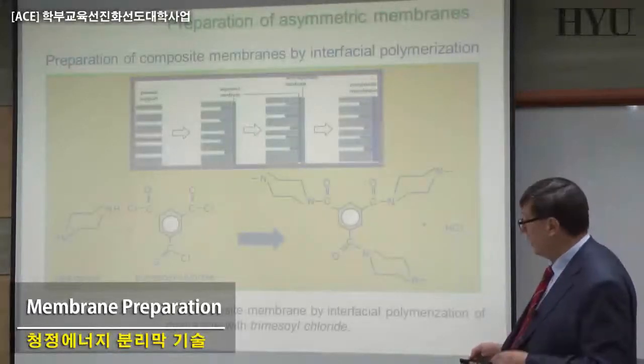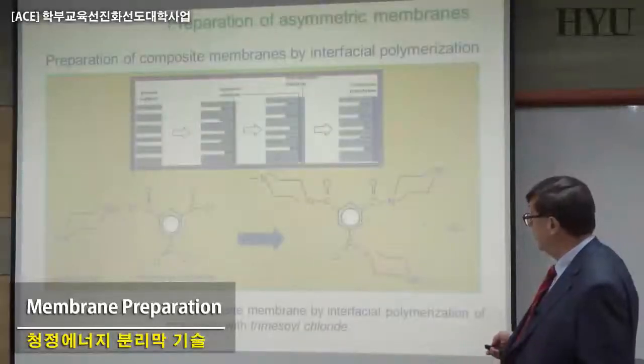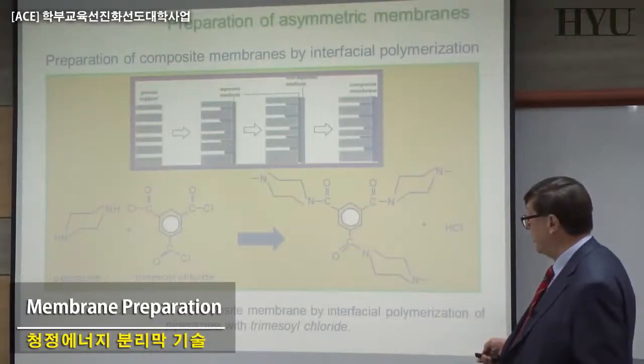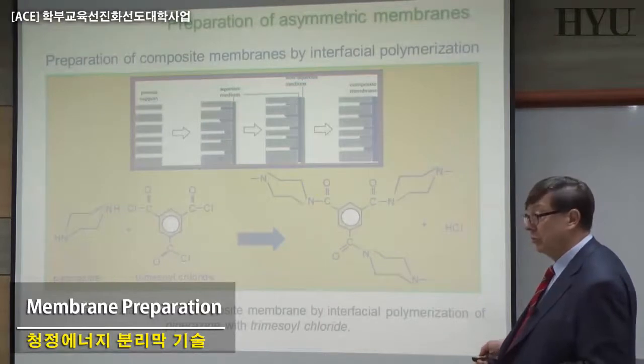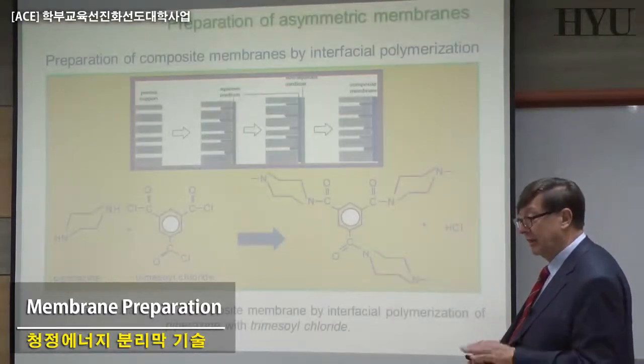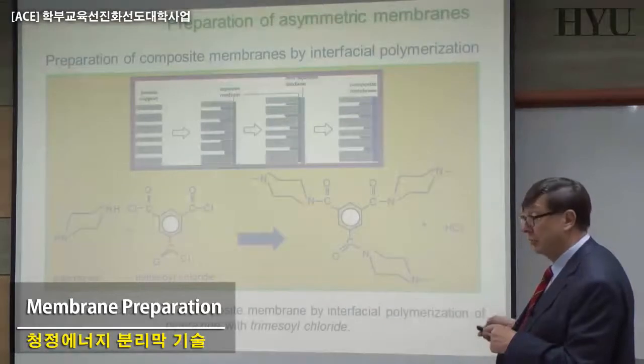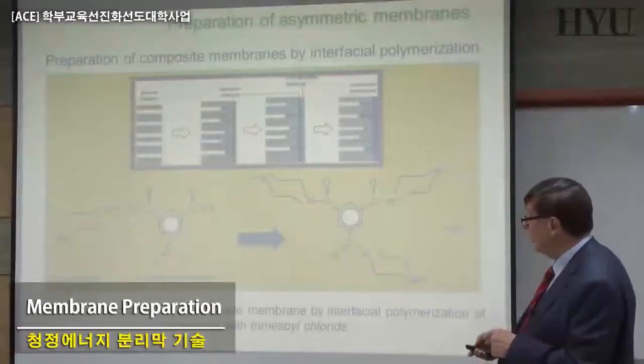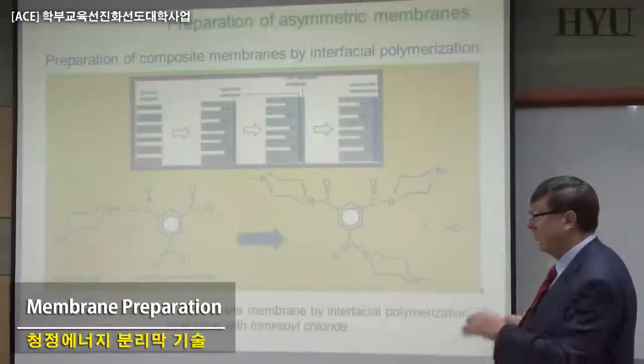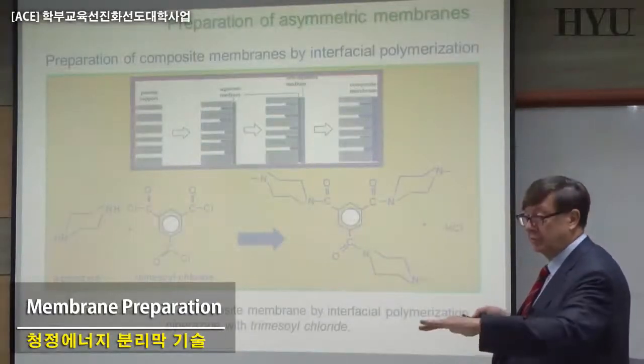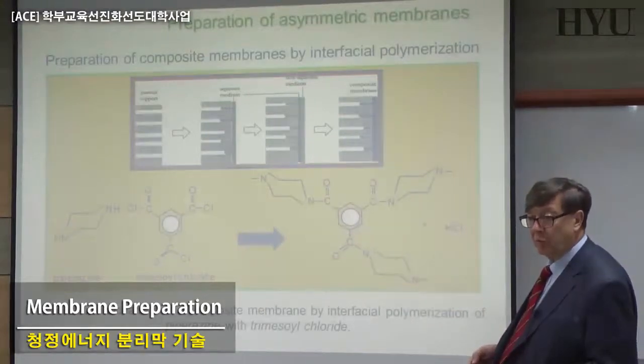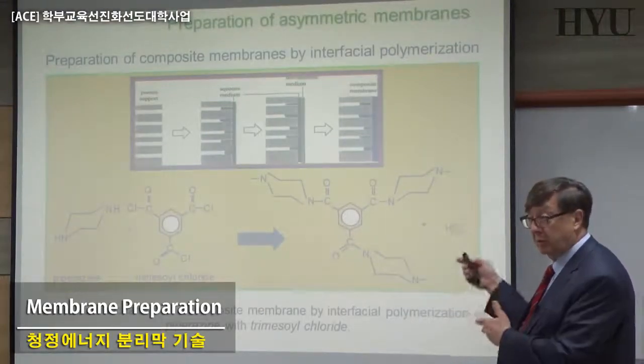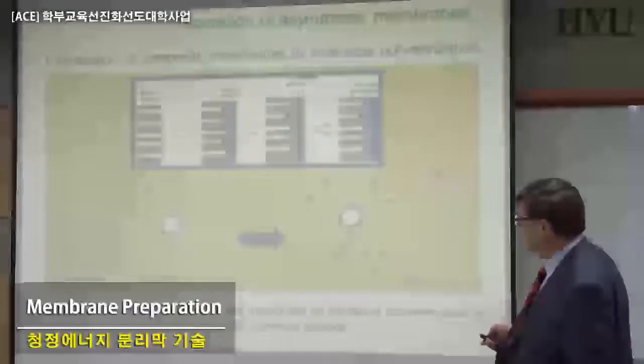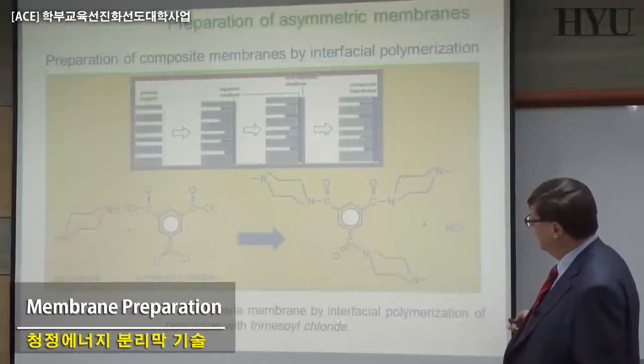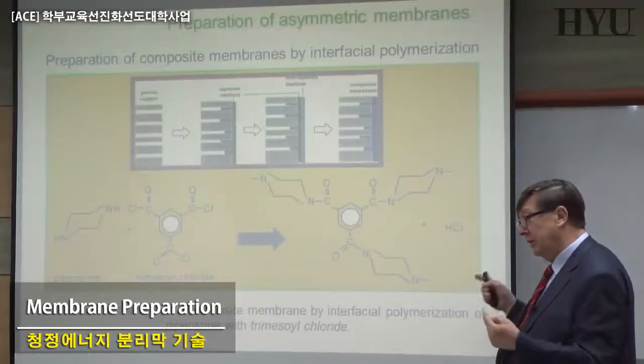We started from polypiperazinamide. This piperazinamide, which is also one of our patents, by the way, has a formation mechanism of composite membrane by interfacial polymerization of piperazine with trimesoyl chloride. Still today, a lot of the membranes utilized industrially are related to this kind of reaction, in which you form this polypiperazinamide, just a thin layer on the surface of a porous support, which can be polysulfone or polyether sulfone or PVDF and similar.